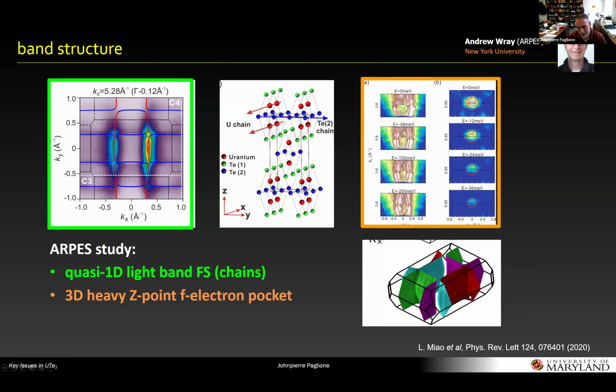Just to note that this band structure, if you calculate DFT for uranium ditelluride, with localized F electrons and no U, you actually don't get any Fermi surface. You get an insulator. So you actually have to turn up U to 1 eV or something like that, or maybe 2 eV, to actually get a Fermi surface, and then you get something like this. The other thing to note is that these states that were observed are actually of the P and D states of the tellurium and uranium. So they're of the light electron states in this experiment, at least.